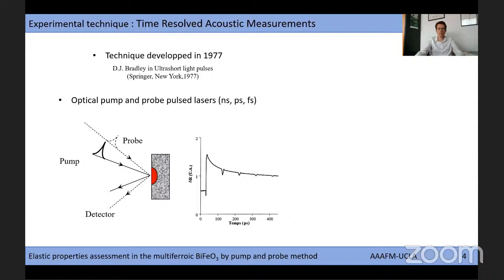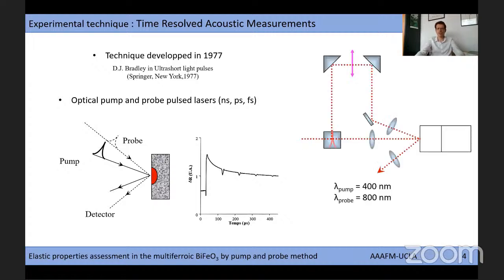These time-resolved measurements allow us to measure sound velocity with an accuracy typically better than 5%, and thus to determine the related elastic properties. Acoustic measurements were performed using a standard stabilized Michelson interferometer sensitive to the perpendicular surface displacement. A 12 nanosecond maximum pump and probe time delay is achieved using a mobile reflector mounted on a translation stage. Both the pump and probe beams are focused with a microscope objective with a numerical aperture of 0.9 fixed on a piezoelectric stage.